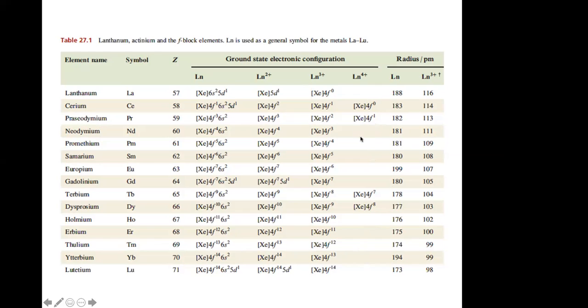A lot of this has to do with the particular stability of lanthanides with an f0, where you have no f electrons, an f7, where you have a half-filled set of f orbitals, and an f14, where you have a completely filled set of f orbitals. As we'll see, the lanthanides are essentially ionic in how they bond with surrounding ligands. And those electron configurations provide particular stability.